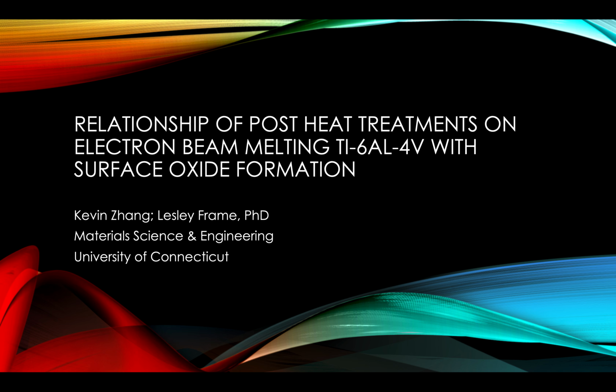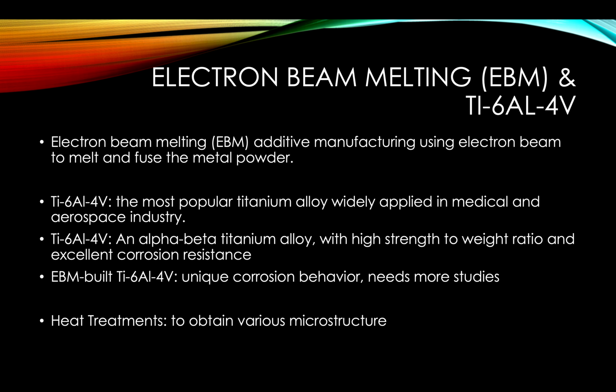Today I'm going to talk about the post-heat treatment on the electron beam melting in Ti-6Al-4V and its potential relationship to the surface oxide formation. So, electron beam melting, or EBM, is an additive manufacturing technique using an electron beam to melt and fuse the metal powder to print out the sample we want.